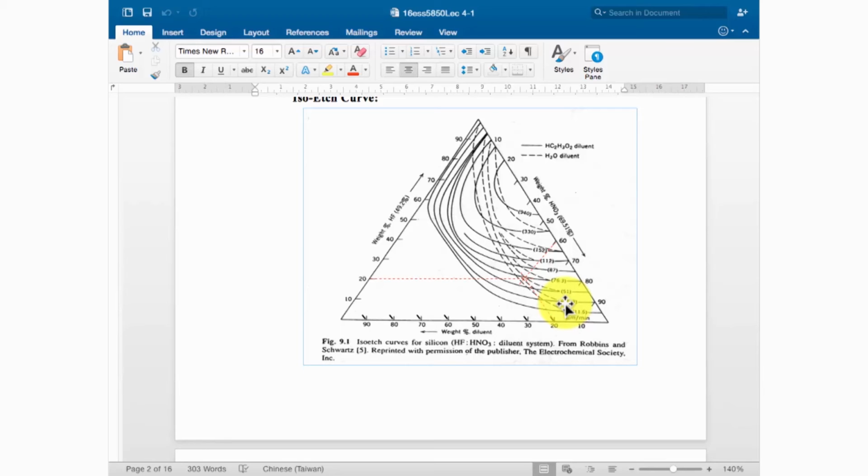So the extrusions, the very sharp parts, can be taken away by the hydrofluoric acid easily. Hydrofluoric acid has enough time to take away the sharp points, the rough surface, on the silicon dioxide. So that's why the bottom one is smoother than the top one.